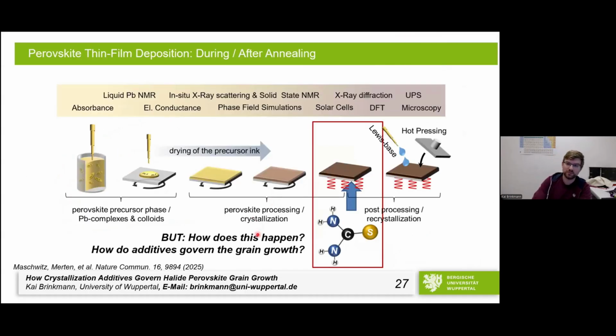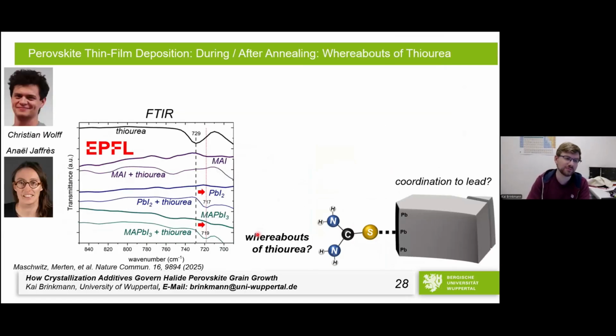So of course, now we would ask, why is it happening? This was also the reason why I was asking where the thiourea is sitting, because we asked ourselves the same question, of course. And the first thing that we did is Fourier transform infrared spectroscopy, just to have an idea of where it bonds to. And it seems like, on the first glance, that we have at least some coordination of the thiourea to the lead. So we did this together with Christian and Anael from EPFL. And this looked like we have it at the grain boundary coordinated to the lead.